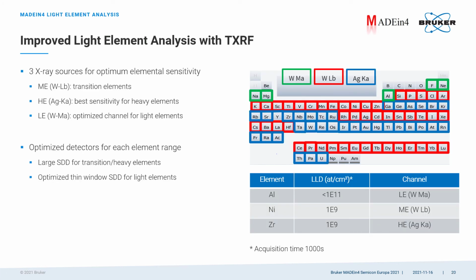The TXRF tool has 3 channels, each optimized for a group of elements. We have a channel for the measurement of transition elements marked with a red box in the periodic table on the right-hand side. The heavy element channel measures the heavy elements marked in blue. The improved light element channel has a high sensitivity for the light elements aluminum, magnesium and sodium. And we even could see fluorine in certain samples.